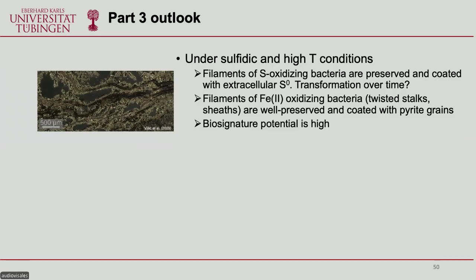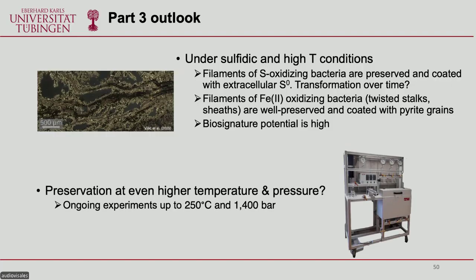To summarize, under sulfidic and high temperature conditions, we see that filaments of sulfur oxidizing bacteria can be preserved and are coated with extracellular elemental sulfur. There may be a chance for the sulfur then to be replaced by pyrite, but we have not seen this in our experiments. In comparison, filaments of iron oxidizing bacteria are well preserved and fully coated with pyrite grains. And so the biosignature potential for them is quite high. We are then continuing the experiments to look at preservation at even higher temperature and pressure. We have ongoing experiments up to 250 degrees Celsius and 1,400 bar.